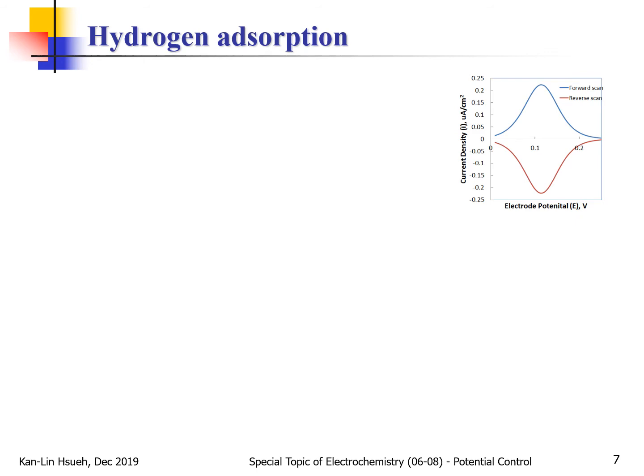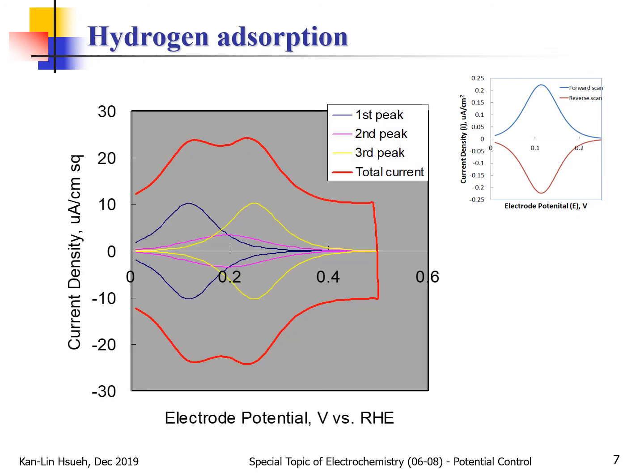So for hydrogen adsorption on the platinum surface, keep this in mind. Actually we should get multiple peaks, because hydrogen adsorption on platinum depends on crystal structure. So usually they have 3 peaks, at say the crystal 100, 110 and 111. The different crystal structures have a combination of these 3 peaks, and it comes up with an overall peak behavior, something like that.